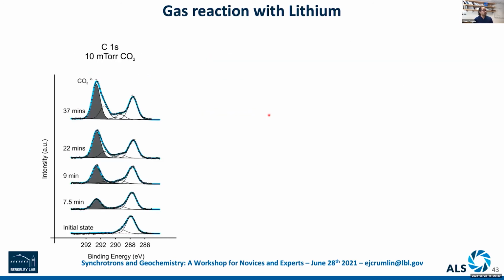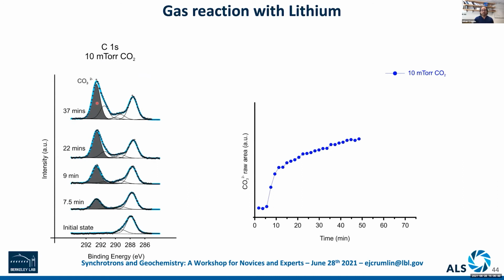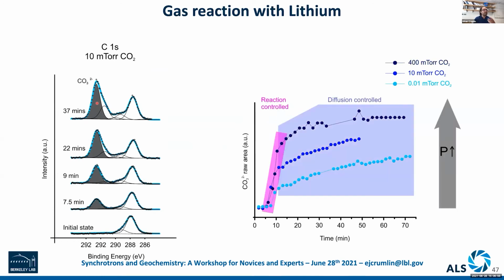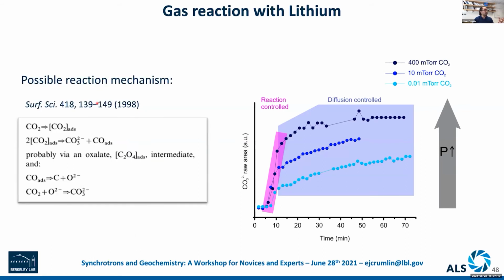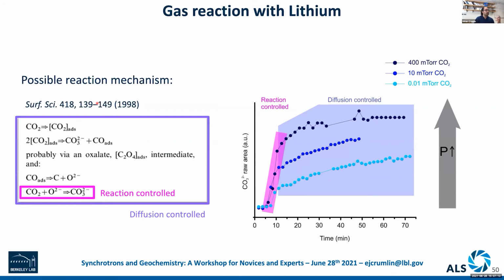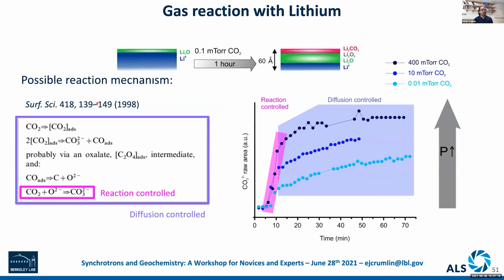If we look at the spectra more specifically, we can see the growth of this carbonate happen as a function of time. If we plot all of the data as a function of time, this is where we can get dynamic kinetic information. We can collect it as a function of time for the different pressures we're doing, so lower pressures or higher pressures. And then that allows us to break down where there are potentially reaction controlled regimes from diffusion controlled regimes. So this gives us the idea of nucleation and growth dynamics with regards to these transformations of interfacial properties. And then from this, we can start to extract different reaction mechanisms that are controlling the types of growth and the behavior and properties with regards to these interactions.